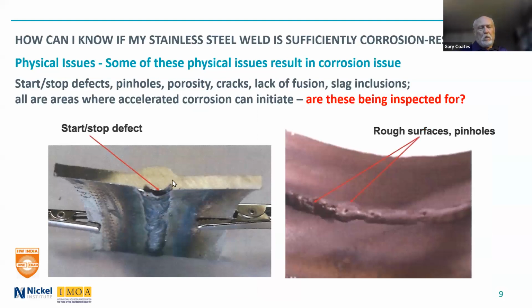Also, it is always important to look at the inside of the pipe some way, and of course things like rough surfaces or pinholes are bad, and in most cases that is really a rejectable defect that should be repaired. And again, the welder actually knows what it looks like on the inside. He's seeing whether he's getting gas evolution causing a pinhole or a rough surface because he perhaps hasn't purged it properly. But he really knows that.